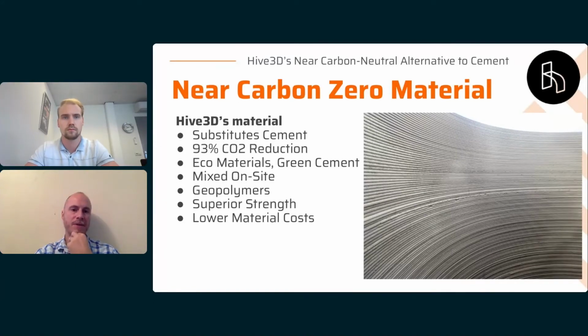So what we currently print with tops out at between 5,800 psi and 6,500 psi is what our testing currently shows. After 7 days, it's about 3,200 psi, and then over the course of the next 20 days or so, it gets another 3,000 psi in strength. So compared to just a regular, high strength concrete mix, it's usually in the 5,000s, so 5,000 to 5,500 psi. So it's a little bit stronger than a normal mix, a little bit stronger than a high strength mortar as well. And we can increase or lower that strength based on how much binder you use.